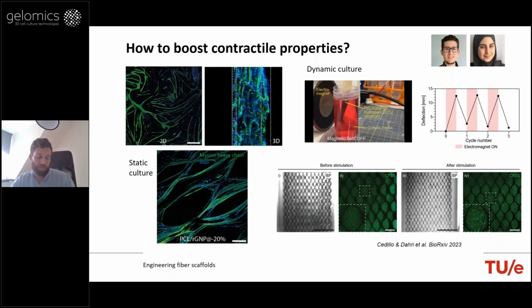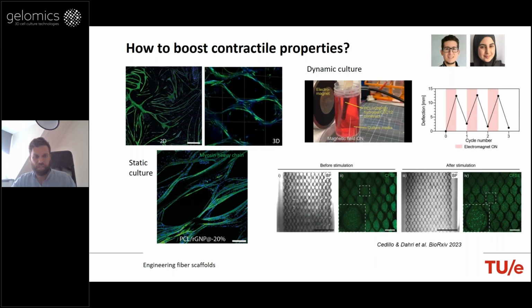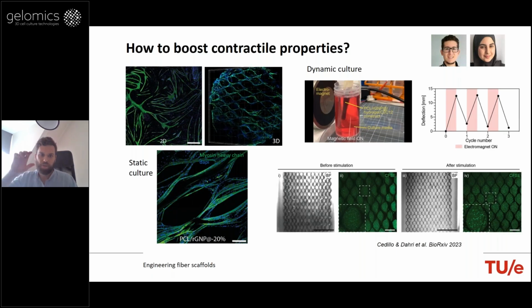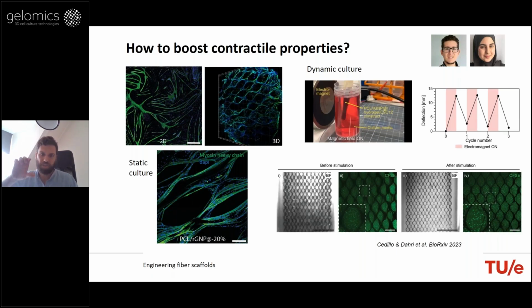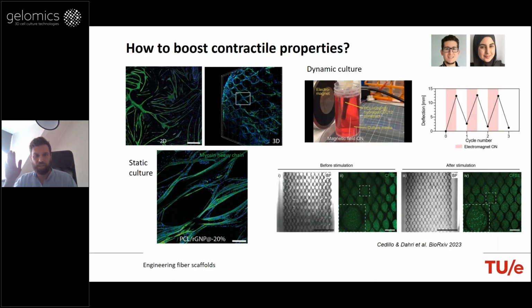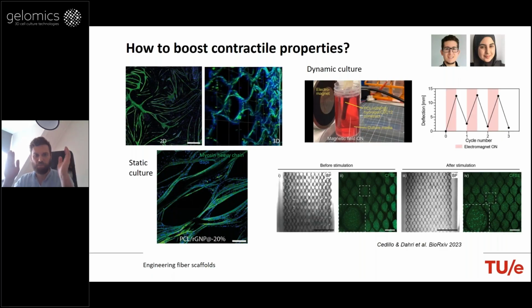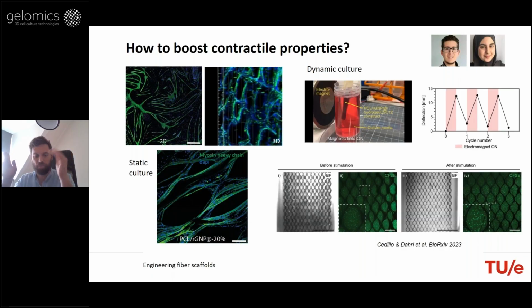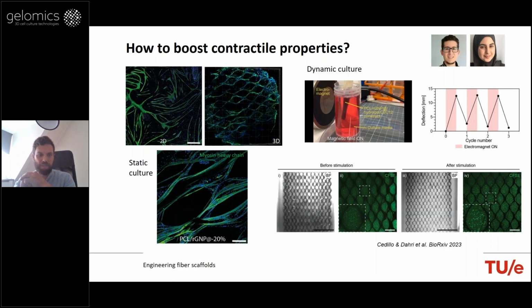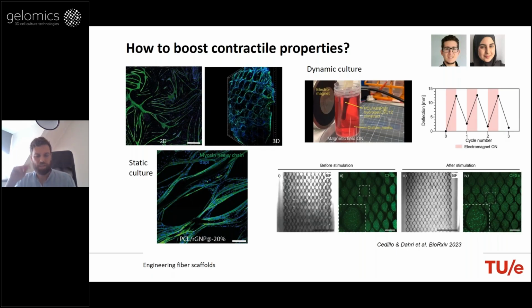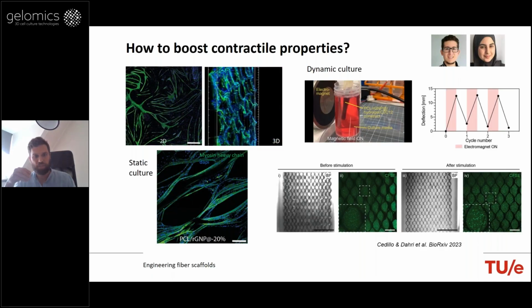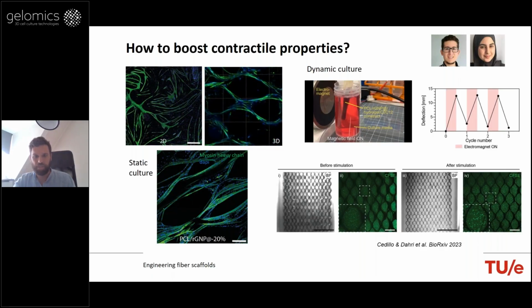This is part of the work that we are still running, and as you see here from the top image are basically constructs with the C2C12 cells seeded inside and then exposed to a magnetic field. So basically we use an electromagnet to either put on or off the magnetic field, and that basically induced the deformation of the construct. And then we look at the cell distribution inside of the construct before and after the stimulation. And what you see here from the bottom is that the cells were within the construct after, in this